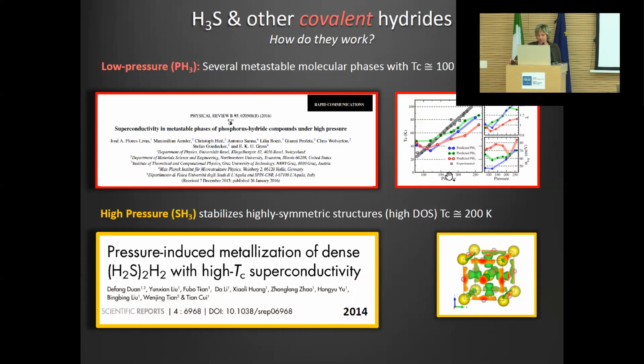And something else that we found in this compound: from the TC versus P behavior, it was not possible to say what experimentalists were actually measuring. But something which is also very interesting that we understood in this study is that all the phases that we had predicted were metastable, and experiments actually reported that the samples also tended to degrade. So this told us that ab initio methods for crystal structure prediction can predict not only stable compositions, but also metastable compositions, and that one may be able to see them in experiment.